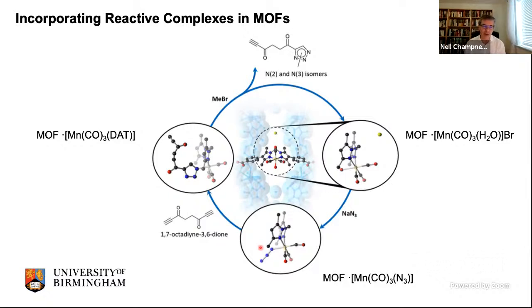And each of the steps in this reaction cycle are characterized by single crystal X-ray diffraction. So we know exactly what the product is at each individual step of the reaction. And that's kind of fun, and suggests that we can start to do this for other types of reactions as well, and study reaction processes within the framework, determining the single crystal structure of each of the steps as we go through. And there's no real reason why it has to be a metal complex. You could do this with organic reactions as well. It's absolutely the same. Crystallography might be harder, but basically it should work.